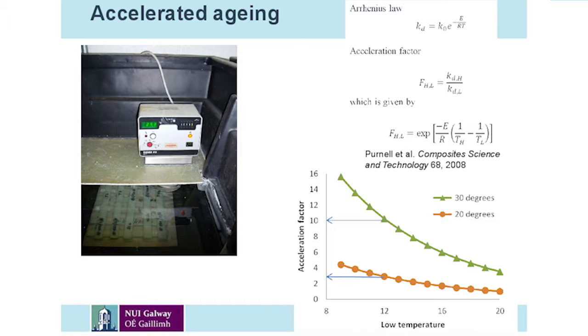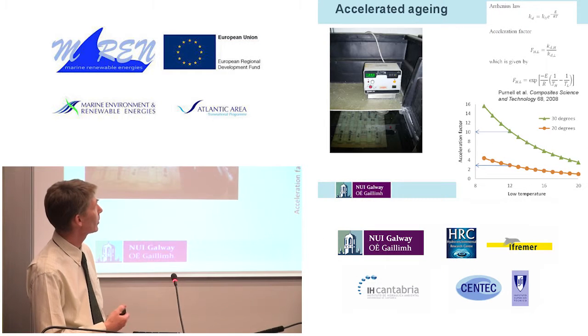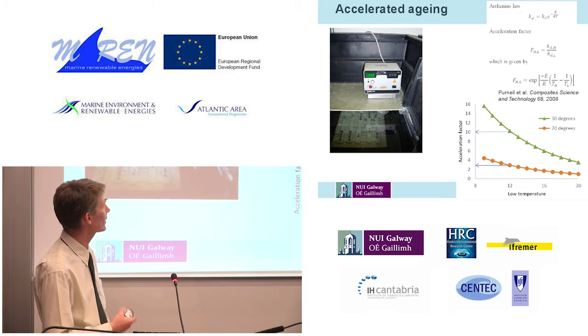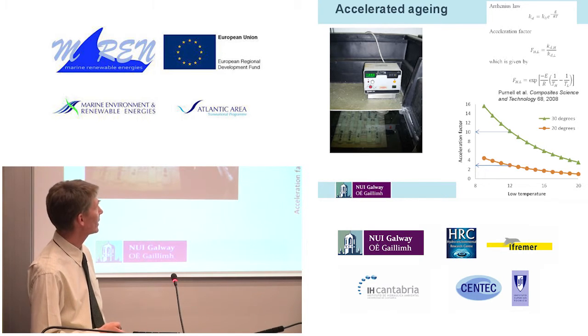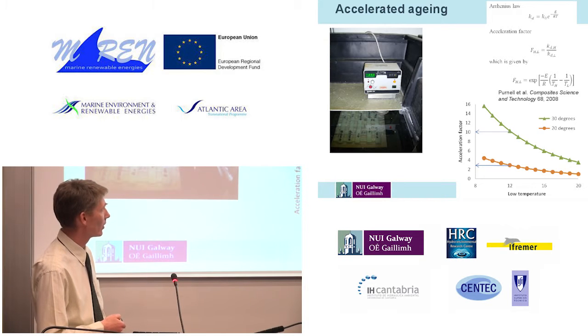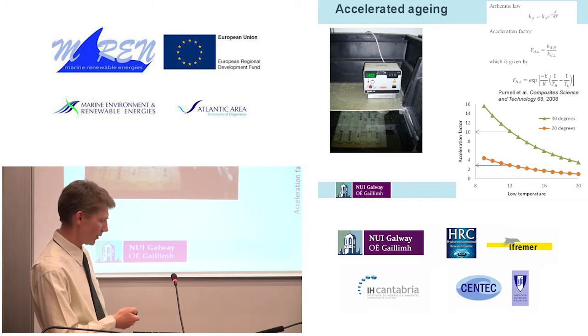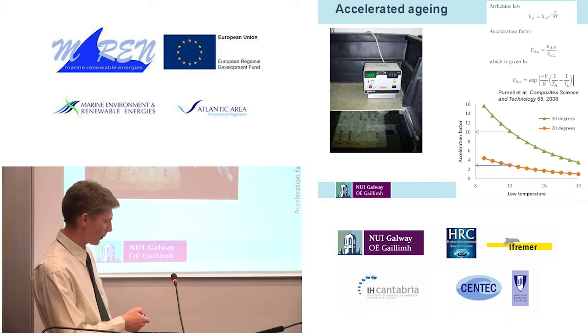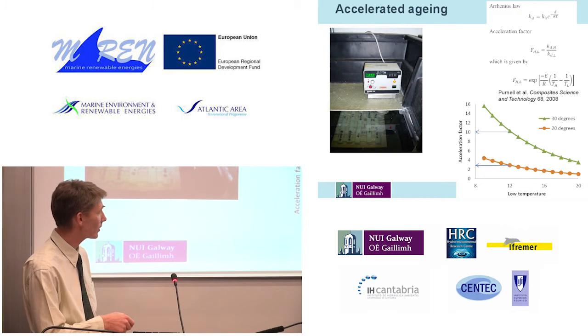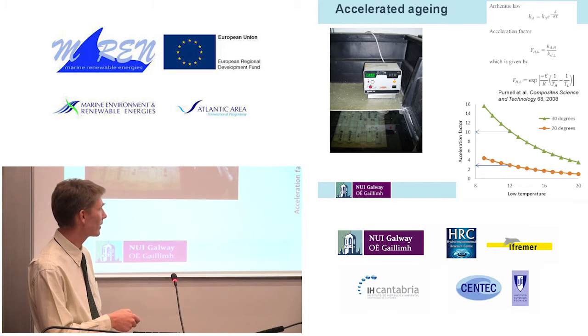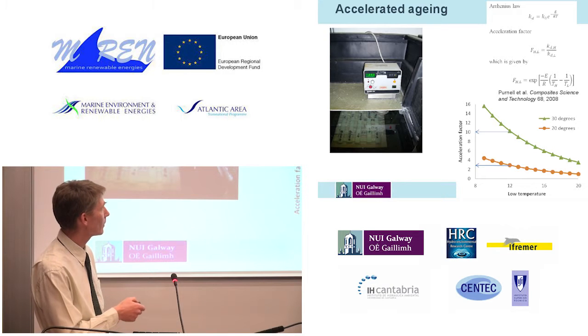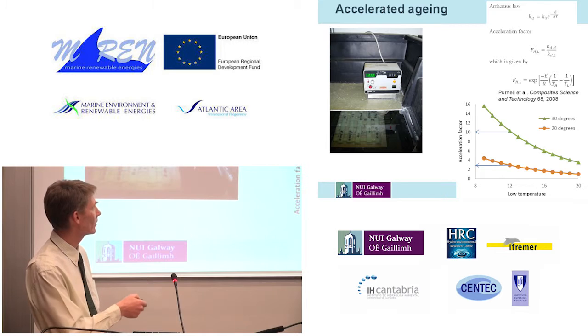So for me, when I was doing the research to investigate the effects of water immersion, I started out by putting some material samples into a warm water bath to accelerate the water absorption process. Basically, water absorption into a polymer is a diffusion process. So by using the Arrhenius law, we can get an estimate of what sort of acceleration we're going to get of the diffusion. It depends on what low temperature you pick, and what the temperature of the water is. In this case, I've decided that essentially the sea temperature around Ireland will be about maybe 12 degrees on average, and by using a water bath temperature of 30 degrees, I get an acceleration factor of 10.